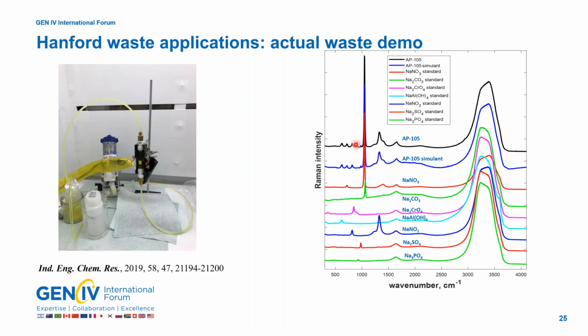So we've taken this AP105 and we put it in one of our flow cells, or in a flow loop. This is the AP105 waste here. It's straight AP105 waste. It's not been processed in any way except to take the cesium-137 out by ion exchange so we can have it contact handled in our open face rad hood. So we have a pump that we're pumping it through our flow cell. This is a cuvette flow cell. We have a Raman probe. This is fiber optically coupled back to our spectrometer. We're able to shine light into our flow cell and measure the AP105.